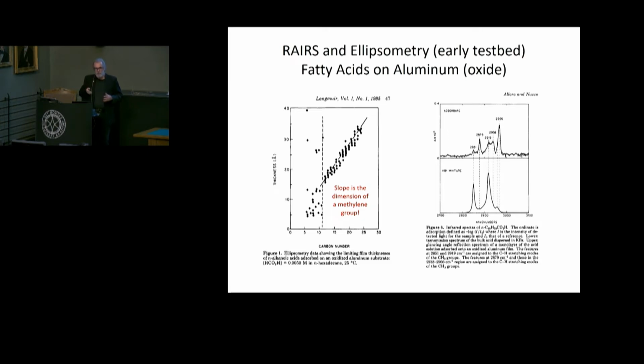Okay, so it says there's something amazing that happens in this material, and it shows that the controversy in the literature as to whether these films are disordered or ordered actually reflects the experimental difficulty of preparing these films, because the substrates tend to contaminate in the ambient environment, and you're doing chromatography, sticking things down, and if any impurities are present, they may adsorb more strongly than the molecules you're interested in, and that complicates the data and the organizations that emerge from an assembly process. And you see that in the IR data shown on the right.